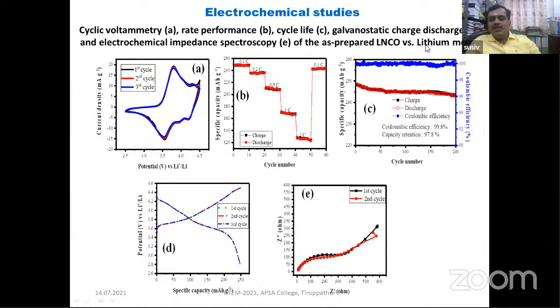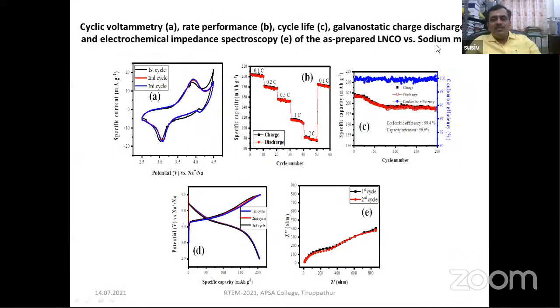So it has been shown versus lithium metal. See the possibility of lithium metal, how it goes in, how it performs with good electrochemical properties. It gives around 250 milliampere hour per gram, whereas while using it in the sodium battery, it also exhibits around 210 milliampere hour per gram with a similar type of rate capability, and CV gives you the possibility of intercalation of sodium material into the LNCO.